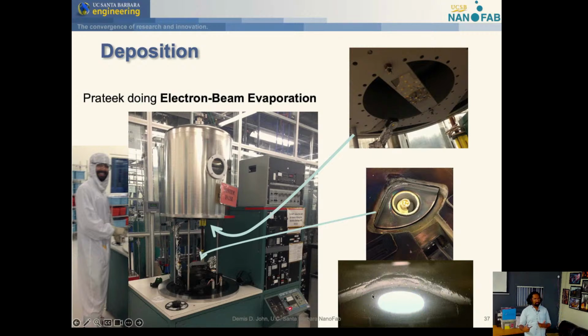You can either heat it with just a resistive heater. In this case, we actually use electron beams to heat it, again, just like a cathode ray tube TV. Heats that up, and that gold will melt and effectively evaporate. It'll boil, so that's why they're called evaporators. And just like steam coming out of your kettle, you get gold molecules flying through the vacuum. As soon as they hit a cold surface, such as your wafer or the rest of the chamber, they instantly turn back into solid. On the chemistry phase chart, that's called deposition, where you go directly from gas to solid. So this is deposition by evaporation.